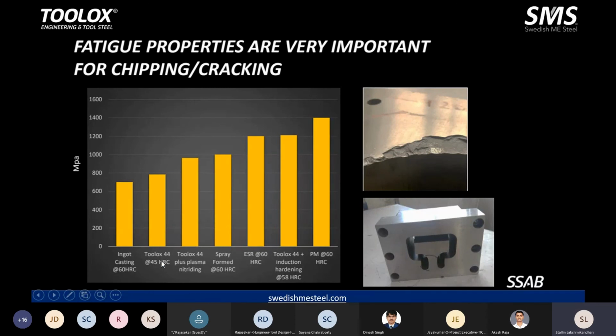Toolox 44 at 45 HRC will give you a good result. But parallel to that, Toolox 44 induction hardened to 58 HRC gives much better results, even compared to your PM steel or even your ESR steel. That's the kind of options the metal can offer you.